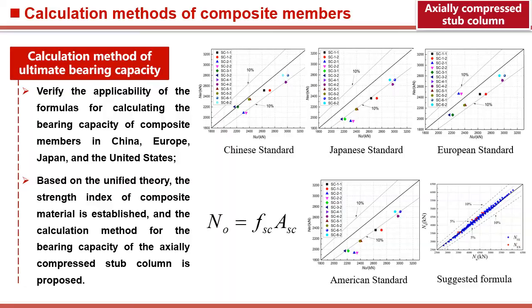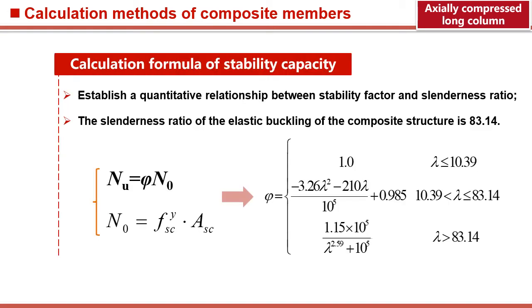Based on the previous theoretical analysis, calculation methods for various composite structures are proposed. Several codes for stub columns under axial compression are compared. It turns out that the codes from China and Europe are relatively suitable, but there are still some discrete data. Therefore, our team established a recommended calculation formula. For long columns, when a certain slenderness ratio of the elastic buckling of the composite structure has been determined, a quantitative relationship between the stability factor and the slenderness ratio is established.